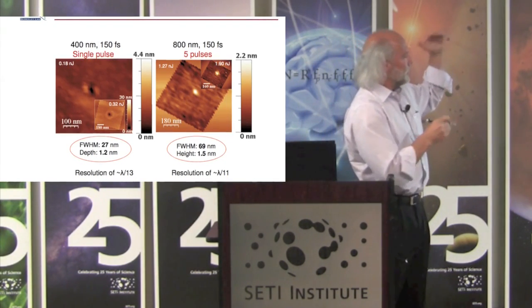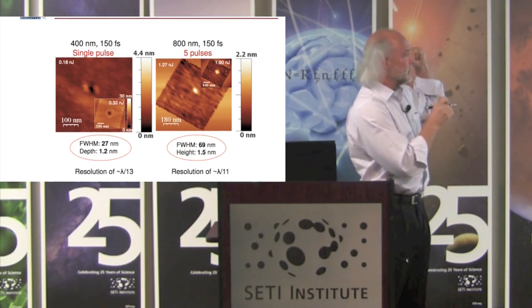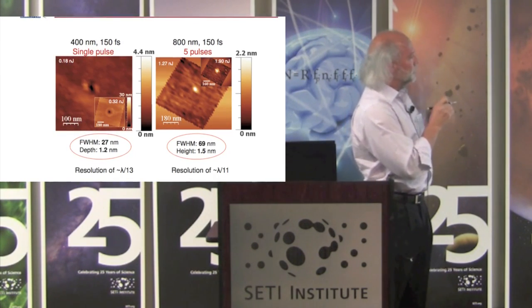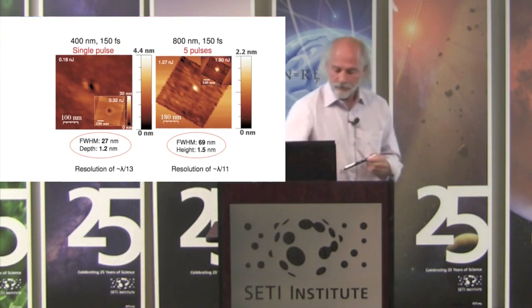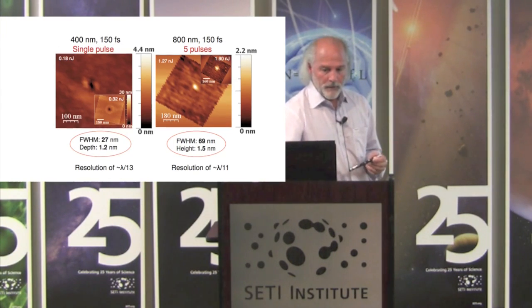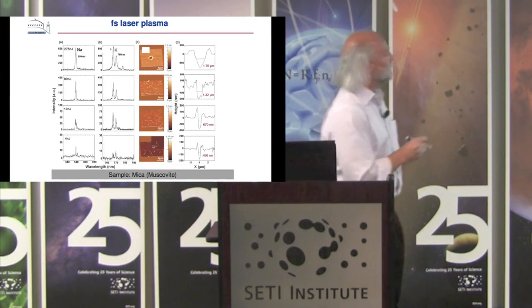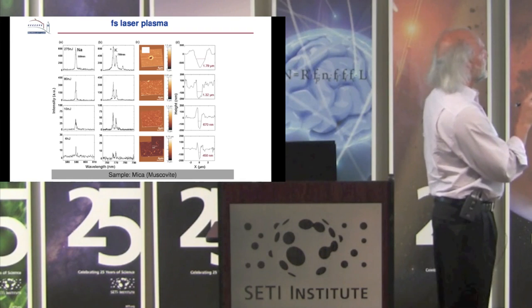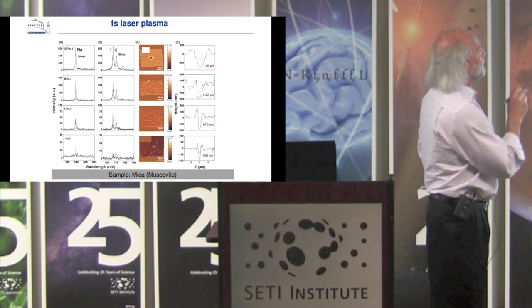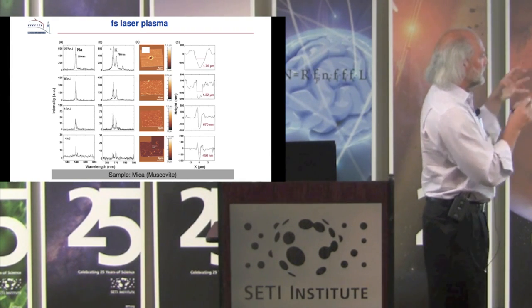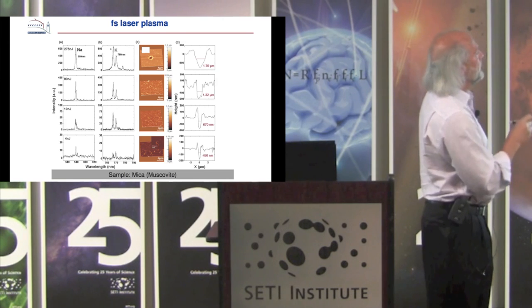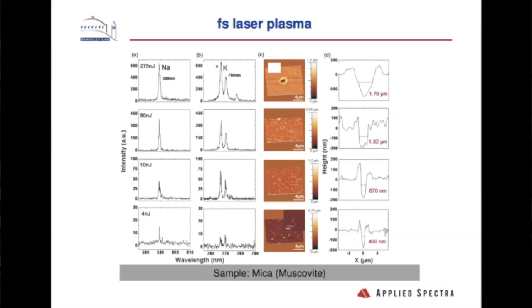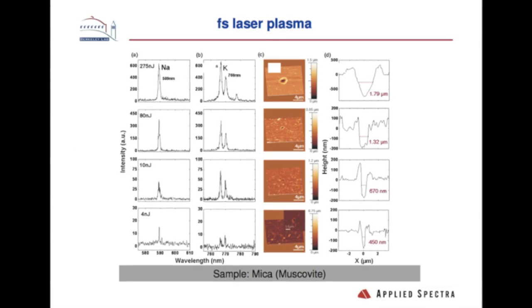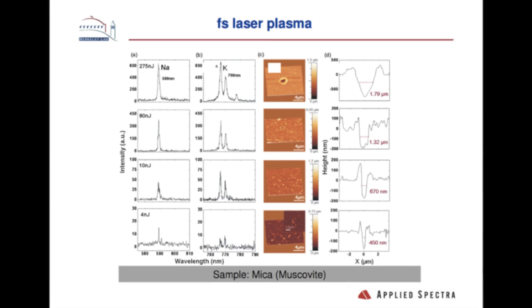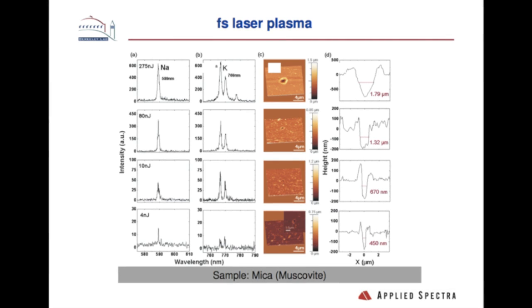So we had to go up. We know we can ablate. We can do sampling down at this spatial size, but we can't see signal yet. So this is where we are. So we backed up. We went to a little bit bigger spot sizes, okay? And now we're just using the femtosecond laser in a very, very tight focusing configuration to where we can see signal. So we use this muscovite sample, and we're looking at the sodium and potassium in this muscovite sample.